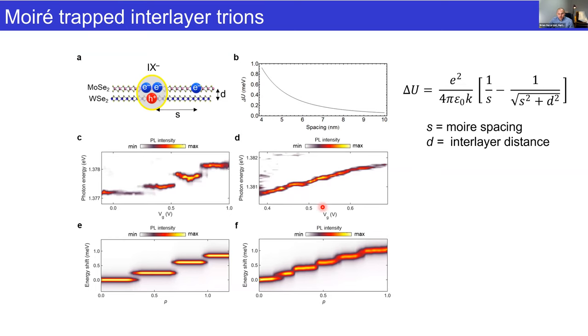And we think that this is because, at least in our Monte Carlo simulation, we get these features arising sort of a slope to these steps from longer range interactions, just adding in a bit of a slope. But every once in a while, we see features like this where they really look like they're just sensitive to the nearest neighbor transition. So perhaps this approach can be used. Essentially, we're using the trapped exciton as a highly localized probe of the environment. And perhaps we can combine this with less local techniques to better understand the Moiré physics.